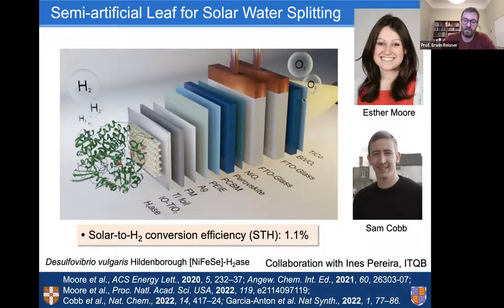So these are catalysts that work at the thermodynamic potential. What this means is that even a couple of tens of millivolts push beyond the thermodynamic limit will drive the catalysis. So from an applied bias point of view, we can actually save a couple of hundred millivolts. And this should really translate into higher activity of our artificial leaves. And long story short, that's exactly what we've seen.